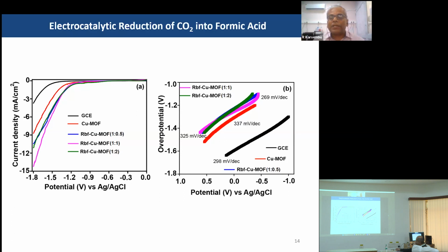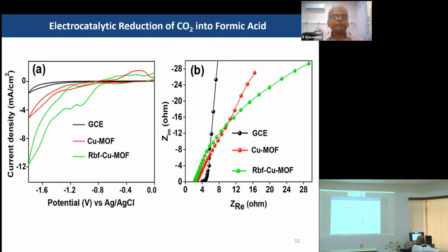We also calculated the Tafel slope, and for the riboflavin modified copper MOF we observed a much lower slope, 269 millivolt per decade, compared to the pristine MOF. That indicates faster reduction of carbon dioxide in presence of this riboflavin modified copper MOF electrocatalyst.